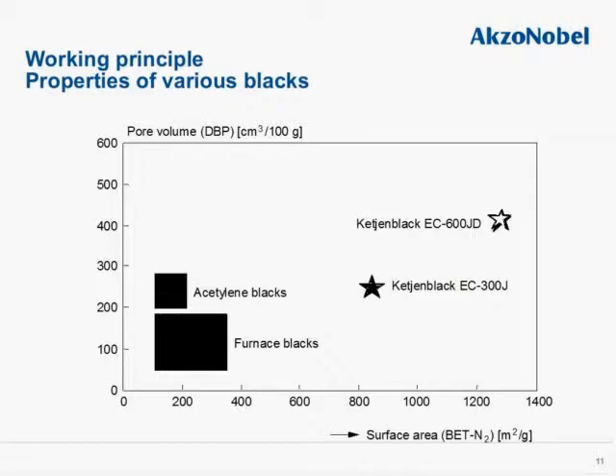Principles of various Ketjenblack. This is a side-by-side comparison. As I mentioned previously, surface area of the Ketjenblack line is high, as well as pore volume. By comparison with some more common types of carbon black, acetylene blacks and furnace blacks would have a similar pore volume as Ketjenblack EC-300, but much lower surface. The surface of Ketjenblack EC-300 is about 800 square meters per gram, and Ketjenblack EC-600JD is about 1,300, so it is almost twice as large as the 300 series. So that is the quintessential difference between the two of them.